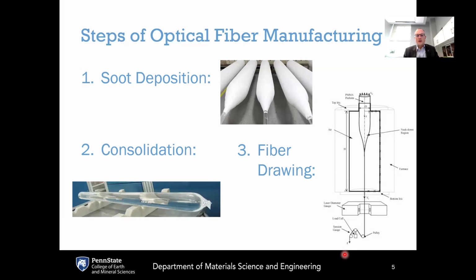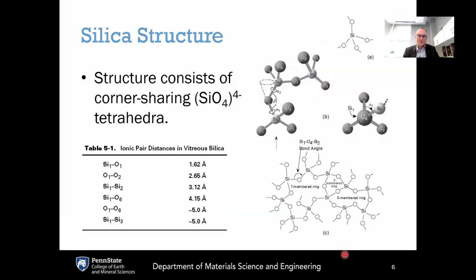And all of this was possible because of the invention at Corning Glassworks by Keck, Maurer, and Schultz of eliminating impurities from silica by going to this outside vapor deposition process, reacting silicon tetrachloride with oxygen to form silica, and doing so in a water-free environment. This was the key invention that enabled the development of long-haul optical communications.